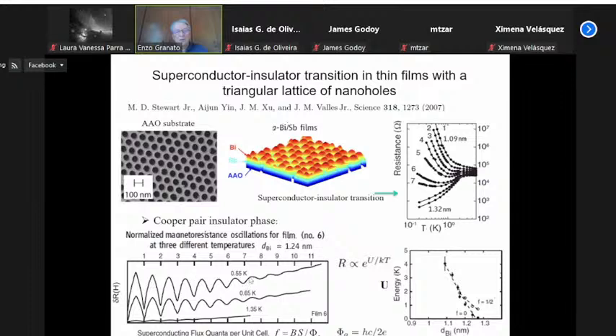The resistivity in the insulating phase oscillates as a function of field, but if you look at it as a function of temperature, as you increase the temperature, this oscillation decreases in amplitude, and the value of the resistivity decreases. Because you are in the insulating phase, the resistance increases exponentially with decreasing temperature, with an activation energy. This activation energy depends on the distance from the transition, and it decreases as you approach the transition point from above. Plotted here on the right is this activation energy as a function of distance from the critical point, meaning the critical thickness, and the behavior is slightly different for f equal 1/2 than for f equal 0. We're going to come back to this point.